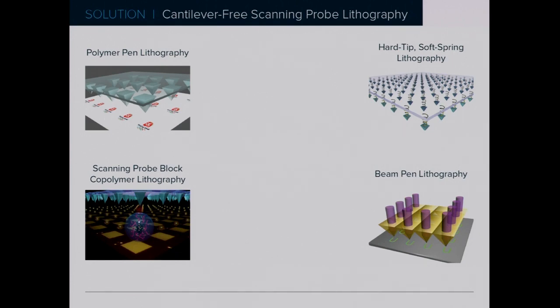backing layer. So we can have the glass substrate, a thin coating of the polymer, that's the compressible material, and then the tips can be made out of silicon, which we can do as well, using relatively straightforward microfabrication procedures where we etch these tips down to very sharp points. Or you could take this structure and you could coat it with an opaque material like gold, and you could create tiny little apertures, just dissolve the gold at the tips.